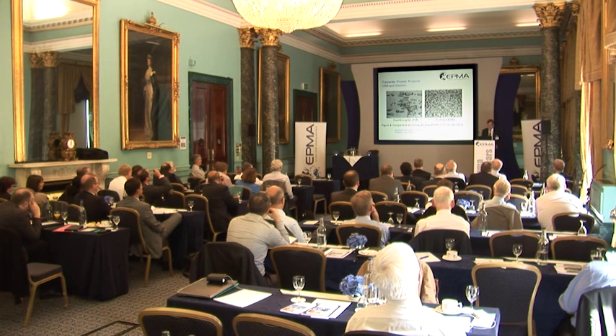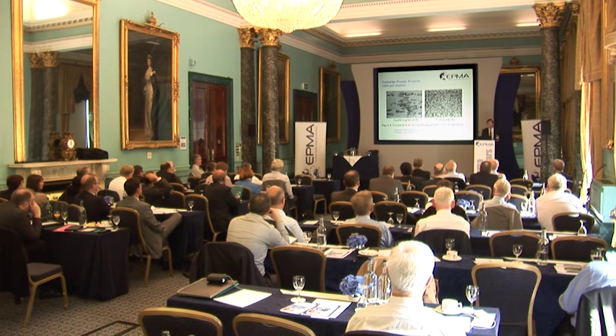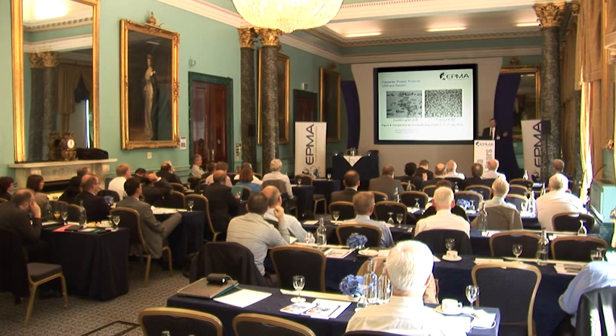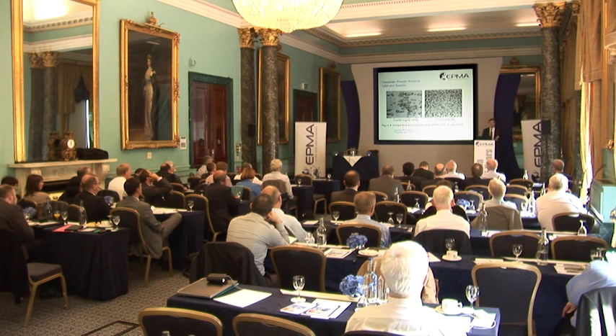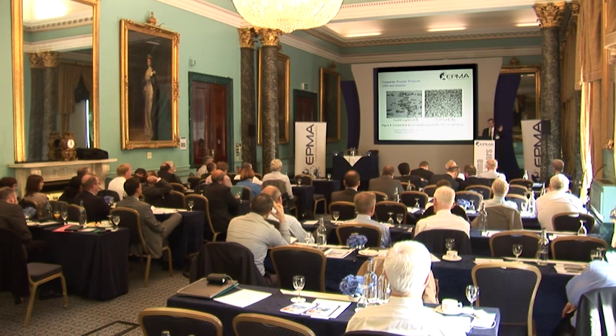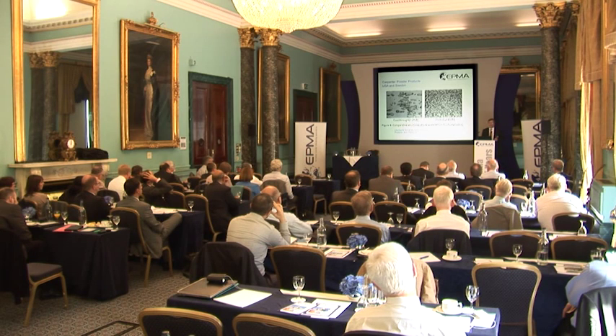This is a publication with unique material. I mentioned there are limitations when you do the casting and forging. There is an interest for storage of nuclear waste or protection against radiation to add boron in the steel. And to the left you can see what's produced at best with conventional casting and forging technology is 1.2% boron. And to the right you can see PM HIP with 1.8% boron and very nice even structure, easily forged.